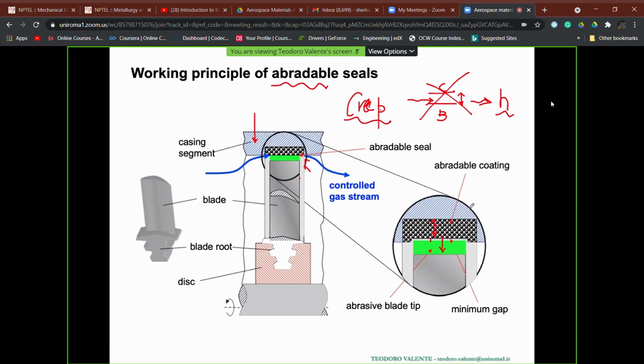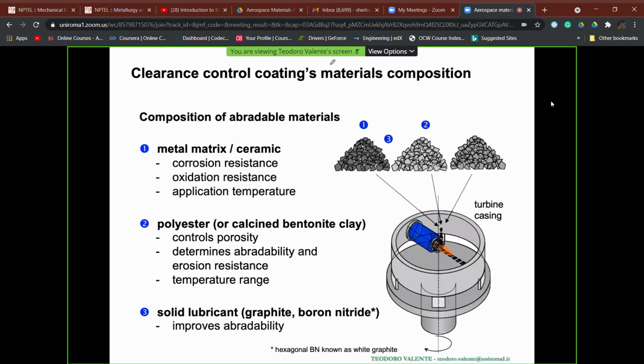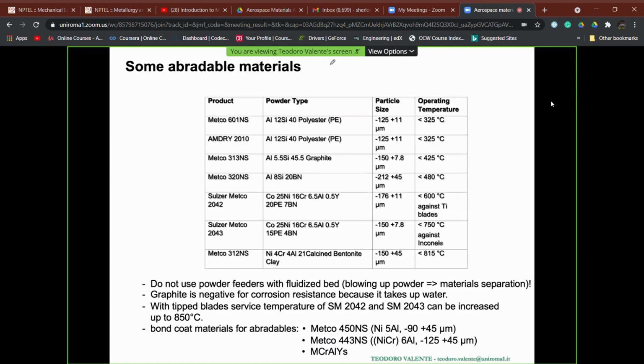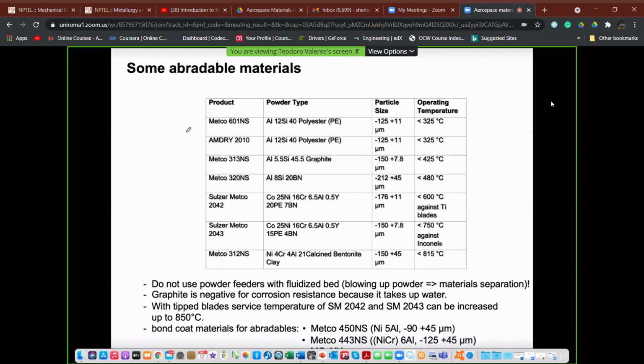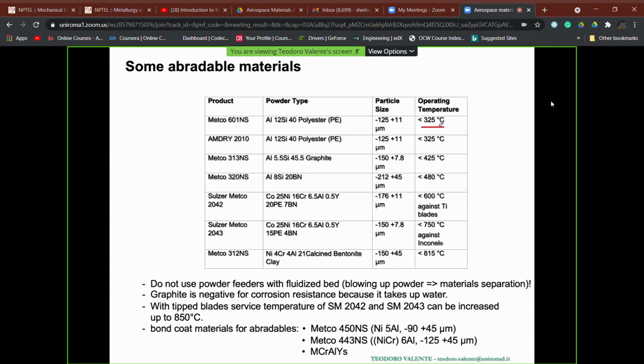And so these coatings must have a special composition, because they must withstand, depending on the section of the turbine, the temperatures of the gas phase, but they must be easily abraded, and this is the reason for abradable coatings, in order to let the rotation of the blade happen without any problem. And what is going to be used? Let's go to see directly this slide. Depending, you see here, on the operating temperature, different stages of the turbine have, and that's again the commercial number, the coating composition which they do have.